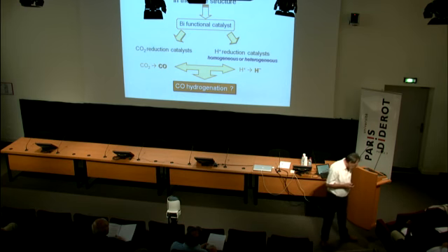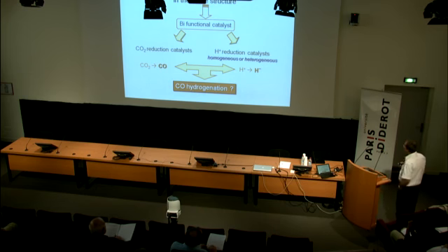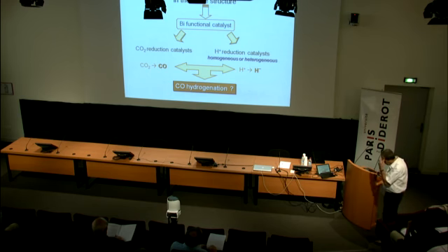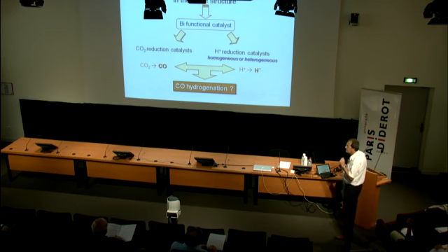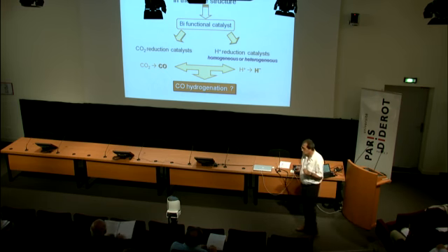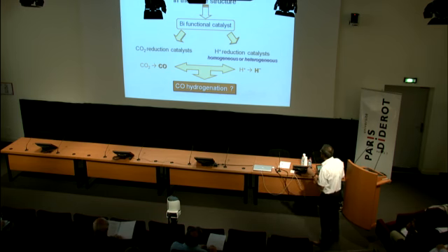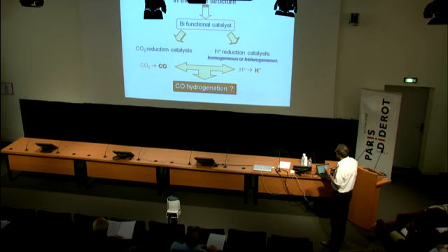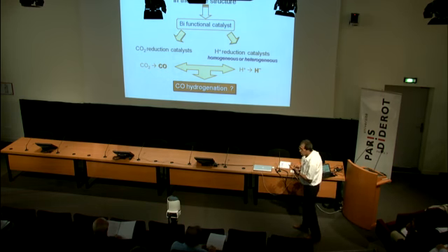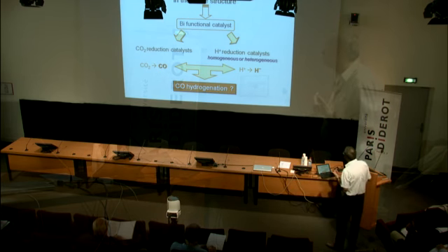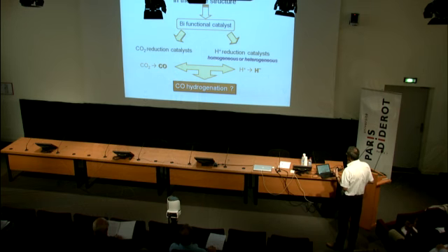So it should be the end of the story, of course, but what could we do more with this system? We were able to have a nice system able to selectively reduce CO2 into CO or formate. So the idea was, is it possible to hydrogenate directly the CO or formate in a bifunctional catalyst? I mean, associate at the same place and in the narrow vicinity another catalyst able to hydrogenate. So we explored two directions, a homogeneous one and a heterogeneous one.